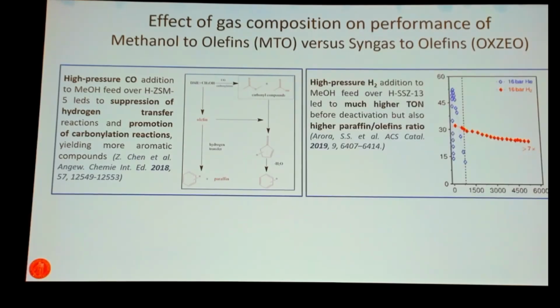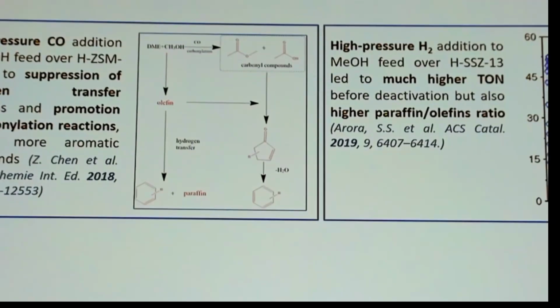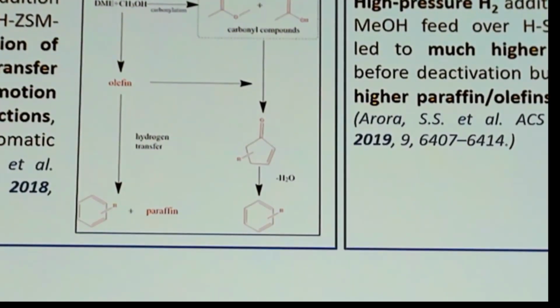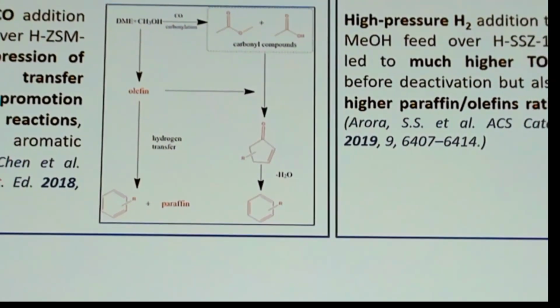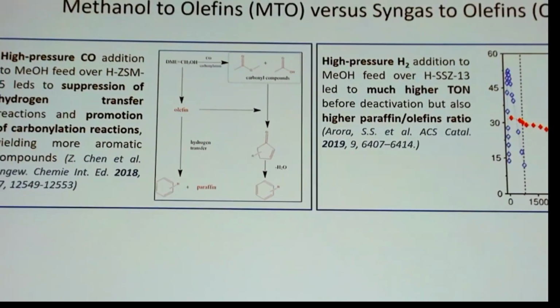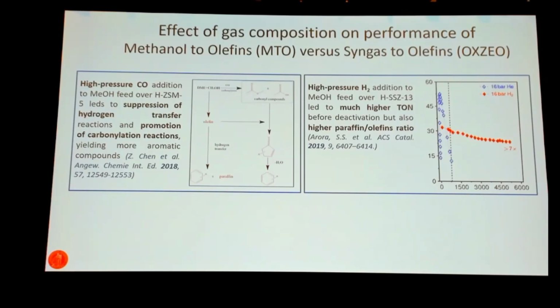And we see here a study from the Hunger group where they co-fed high pressure CO to methanol over ZSM-5 zeolite, and they found a large increase in the selectivity to aromatics and a decrease in the selectivity to alkenes. Normally, those are linked so that you have hydrogen transfer to form alkanes plus aromatics when you do the MTH reaction. But with CO co-feed, they found that they had much more of the carbonylation reaction, so they actually promoted a new route to aromatics formation and suppressed the ordinary route via alkenes.